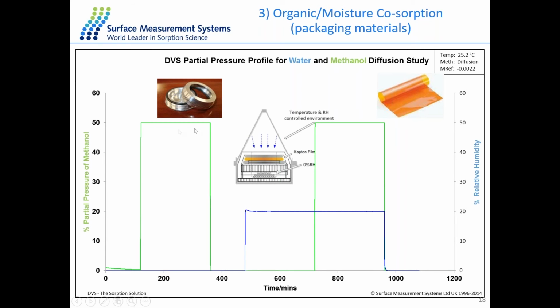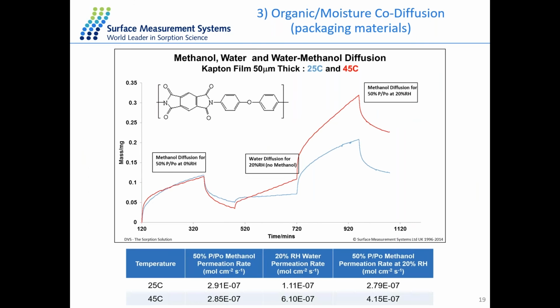The green one is the partial pressure of methanol. So the first stage is the methanol only stage with 50% partial pressure. And the second stage is the water only stage with 20% water. And the last stage is 50% methanol in the presence of 20% water as the background. And we performed the same experiment at both 25 and 45 degrees to study the effect of temperature on those molecule diffusion. So the blue line here is for 25 degrees, and the red line here is for 45 degrees.